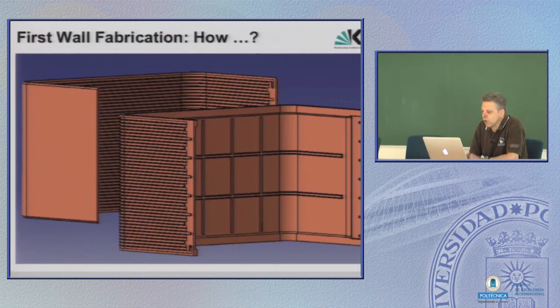There is one problem. This is a cut of the first wall, and you see there are many internal cooling channels. This is a helium cooled concept, so these cooling channels are to cool the first wall. This here is the plasma side, and you see from the dimensions they are rather tiny. There is only 3.5 millimeter wall thickness towards the plasma side. Then we have these many cooling channels with also tiny cross sections, about 14 times 14 millimeter square. And the distance of the channels is also rather tiny, it's only 5 millimeters. If you would unbend this U-bent first wall of the blanket box, the length is approximately 3 meters.